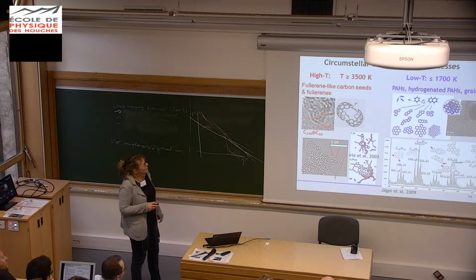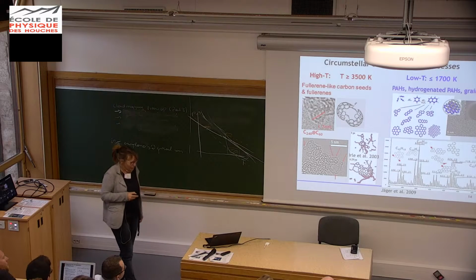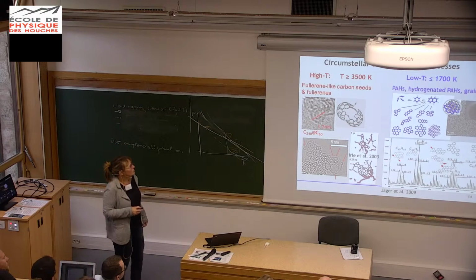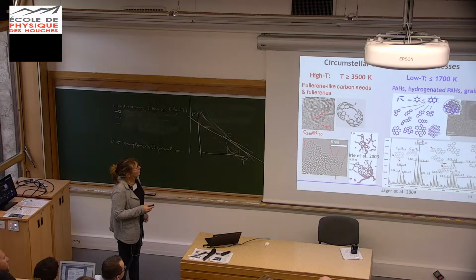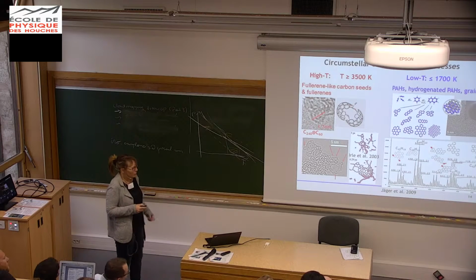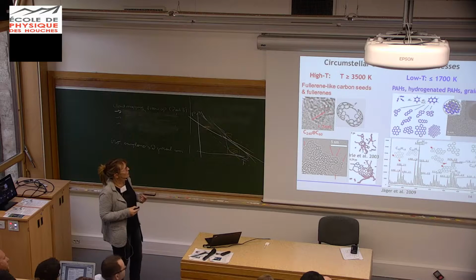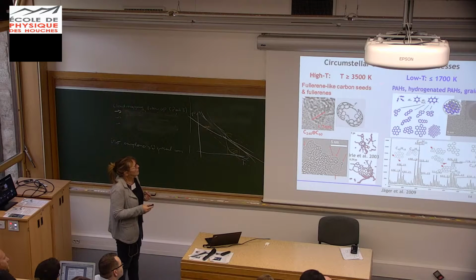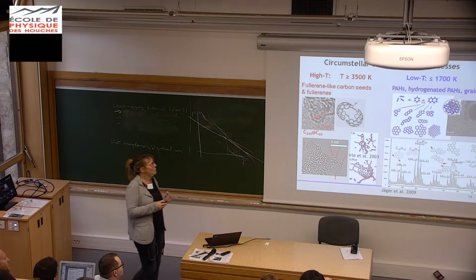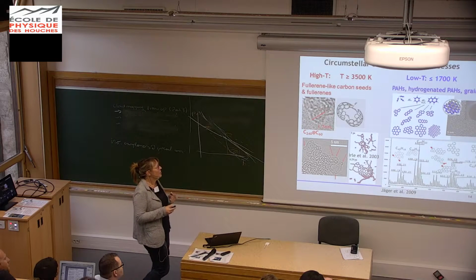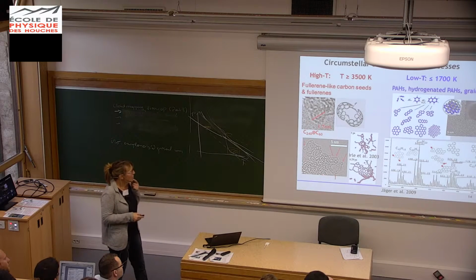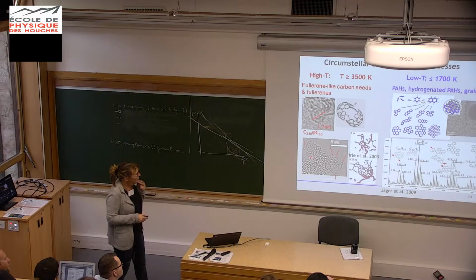So we also studied the condensation of carbonaceous materials. I want to compare what we have seen when we compare homogeneous nucleation at different temperatures. If we condense the carbonaceous material at temperatures higher than 3500 K, then we condense fullerene-like material.